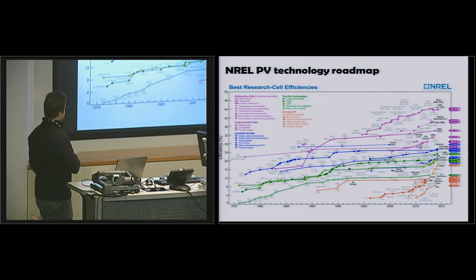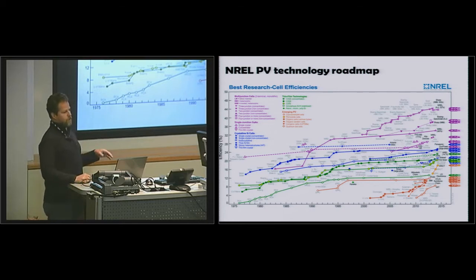The silicon solar cells, that's mostly what you find residential on houses. And then out of the thin film materials, amorphous silicon has been around a long time, but has limits in stability, photostability, and efficiency, so it's sort of stopped being used very much anymore. Cadmium telluride is the big one. First Solar makes cadmium telluride, about 10% of the market. The rest is silicon. And then copper-indium gallium selenide is another thin film material that a lot of companies have been trying to develop commercially.